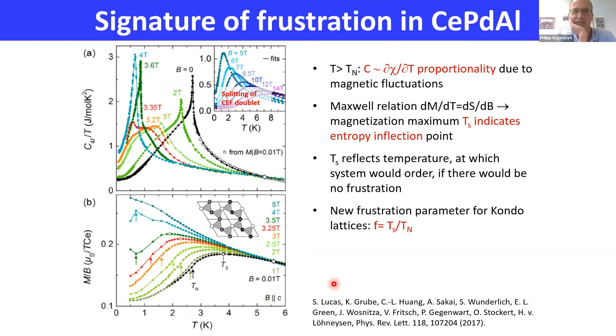But instead, we recognize that at least in this cerium palladium aluminum case, the specific heat looks quite unusual above the magnetic transition, because you see there is a wide temperature range where upon cooling it grows, and this is a range where magnetic fluctuations are getting important. We also found that the specific heat is proportional to the temperature derivative of the magnetic susceptibility. And we see that the susceptibility, or here the magnetization, passes a maximum at a temperature Ts, which is much above the ordering temperature. Since the temperature derivative of magnetization equals the field derivative of the entropy, this means that the line of these magnetization maxima defines a line where the entropy is maximized. So it's an entropy inflection point, which we see here.